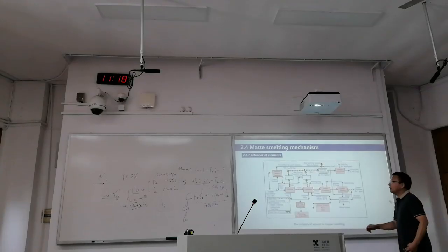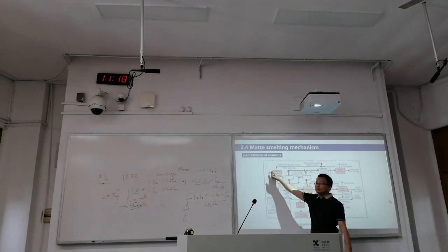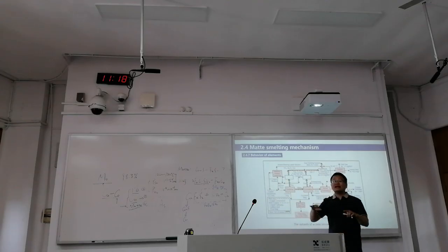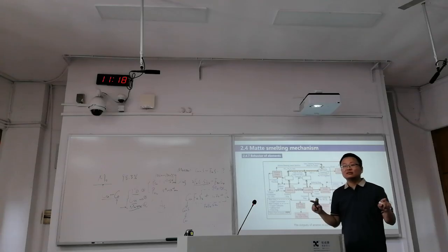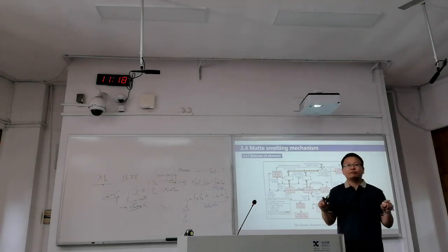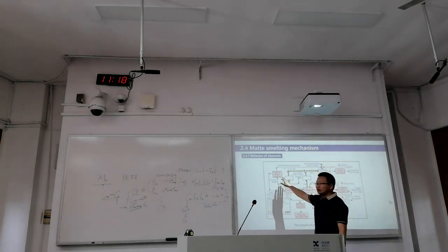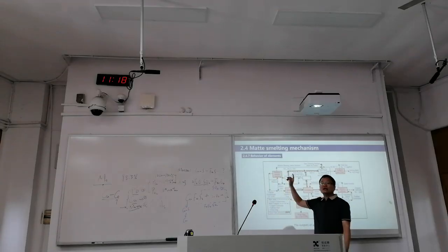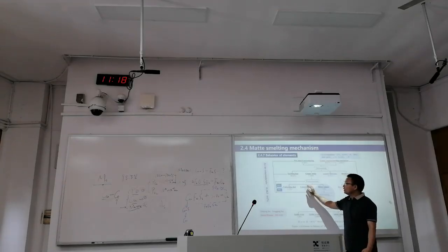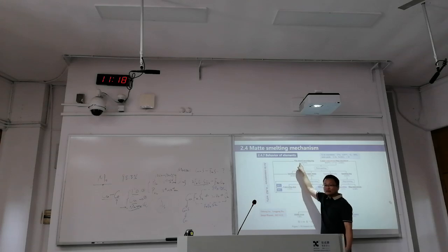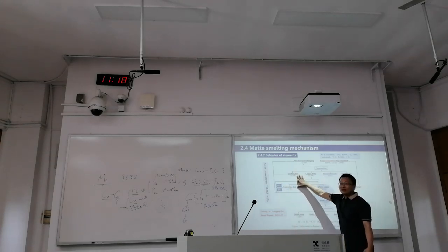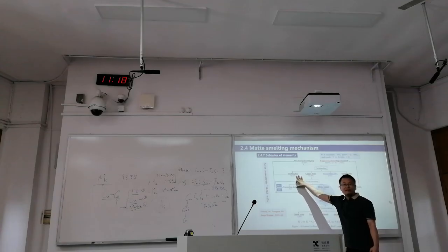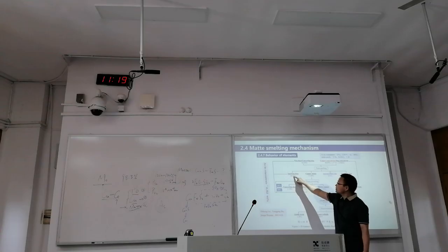I was talking about it when I was organizing, or proposing, the standards for the copper smelter process, and I am recommending that all copper smelters should build a hydrometallurgy unit. They are no longer returning their smelting dust directly. They don't return it directly. They are leaching the arsenic out. They should decrease the values here.